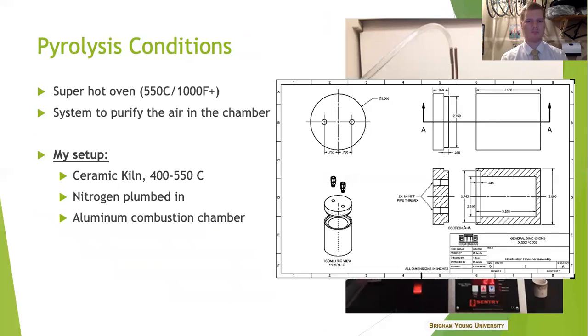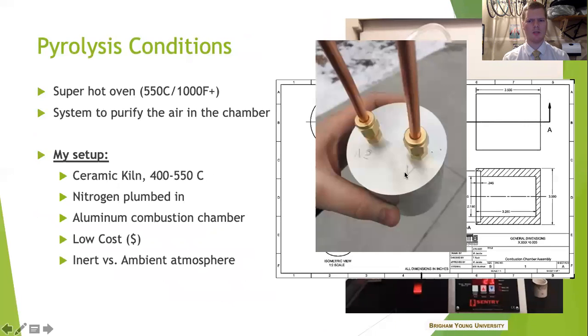So I got this kiln, and I machined a combustion chamber made out of aluminum, and I had a port coming in for nitrogen, so I could get that nice stable inert atmosphere inside, and a vent out for all the off-gassing. And this allowed me to compare, okay, so if I have pyrolysis in an inert condition, it's the favored, typical classic research process for pyrolysis. What if I compared that to no inert gas, just ambient atmosphere in the combustion chamber?